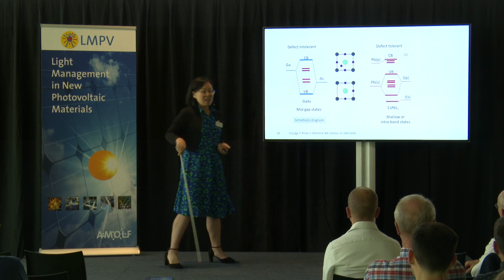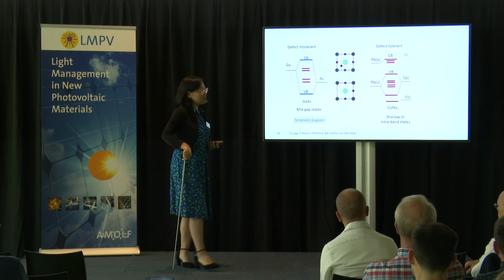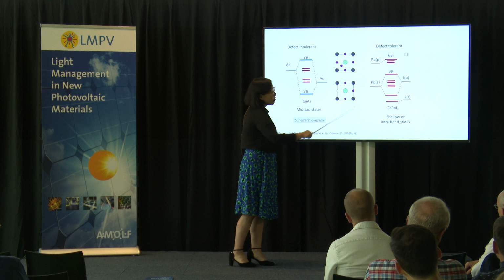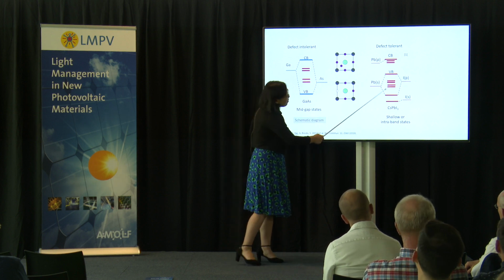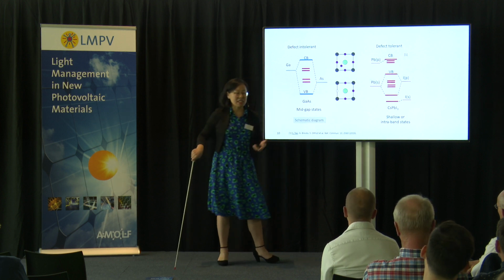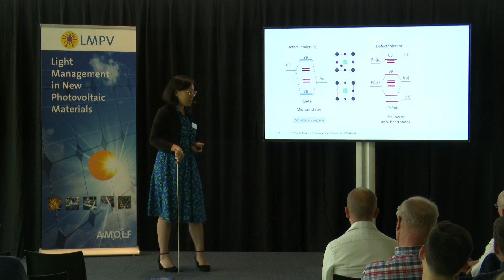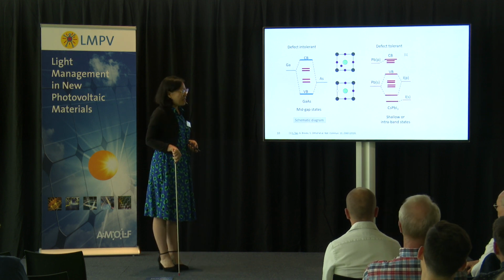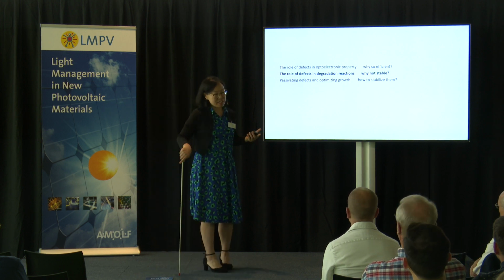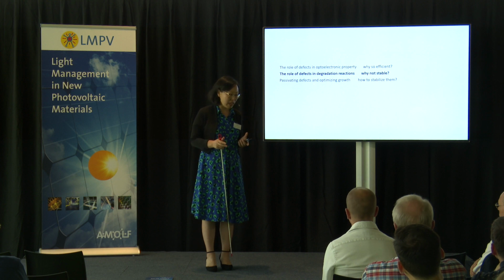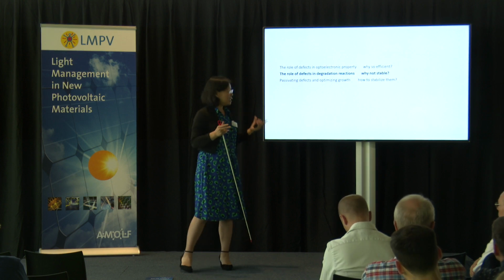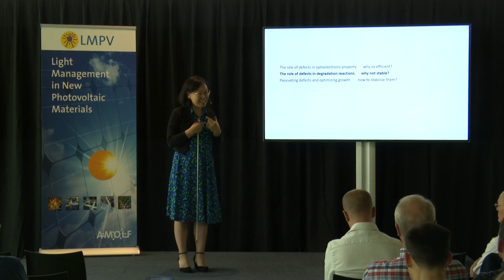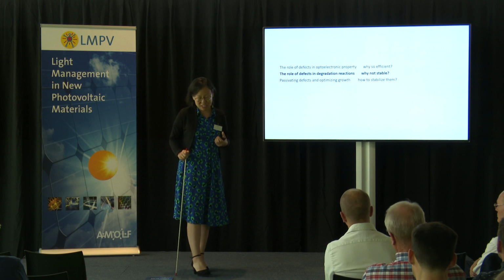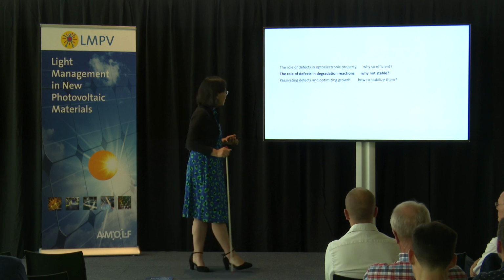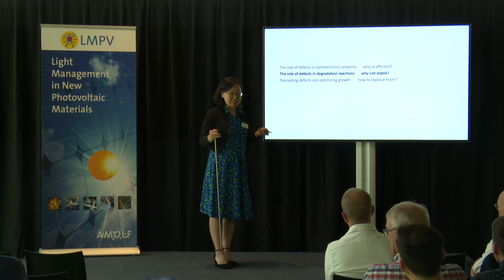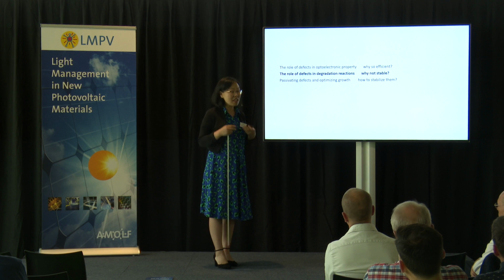And if you look carefully, exactly because the intrinsic electronic structure of the halide perovskites made sure that, even though a lot of defects are there, the defect levels actually landed in the bands or on the edge. This is exactly the fundamental reason why the defects are not harmful for the efficiency directly. But this is not the end of the story. We know this type of material is soft and also easy to make. They're very dynamical. This dynamic property is very, very fascinating for me as a theorist to look at, but they also cause a problem for our solar cells. That means under stress, under light, electric bias, thermal or chemical stress, degradation happens.